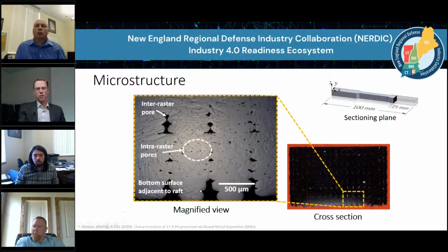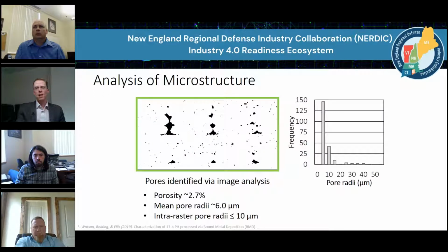At the bottom, this is how the surface roughness looks on the bottom for the prior generation of the slicer. If we zoom into just the section, we can analyze the microstructure and see that in this particular section, it's about 2.7% porosity. Mean pore radii is about 6 microns, with intra-raster pores somewhere less than 10 microns. And over here is the frequency of that distribution.